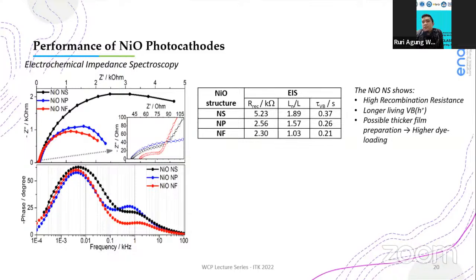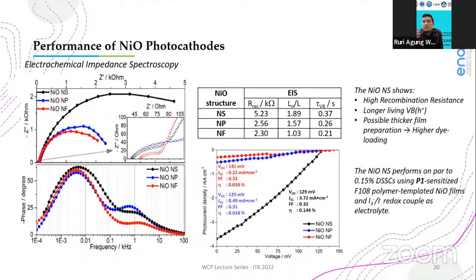So the effective diffusion length also suggests that we are able to prepare thicker films using nickel oxide nanostars by a factor of almost 2, so that the current thickness, which is 1.5 micrometers, can be doubled up to 3 micrometers thick. But from the solar cell properties, nickel oxide nanostars also shows the highest photoelectrochemical conversion efficiency, which I would say is on par with the best reported efficiency of nickel oxide-based solar cells prepared under a similar system. So here we conclude that nickel oxide nanostars, which is formed from beta nickel hydroxide, is promising for further development of photocathode materials.